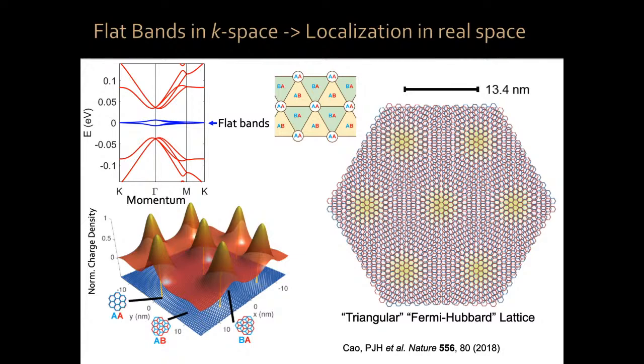Now, I put triangular in quotes because in reality this is a honeycomb, because these AB and BA regions are not equivalent. And I put Fermi-Hubbard lattice in quotes because this object has interesting topological properties which prevent a direct mapping to a regular standard Fermi-Hubbard lattice in cold atoms, for those of you that are experts on that. So then how do we do this?